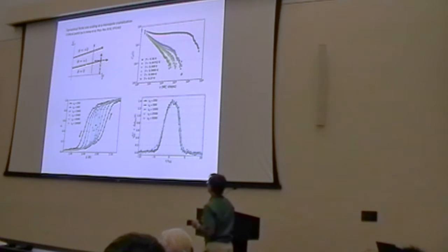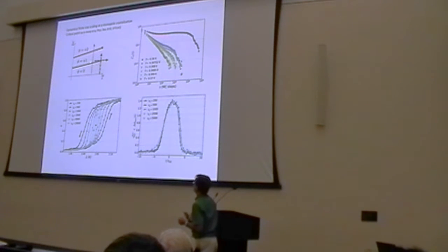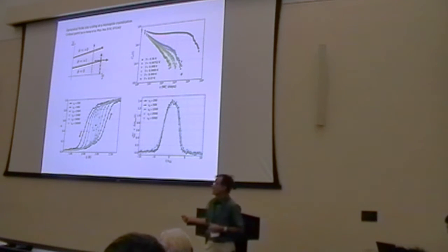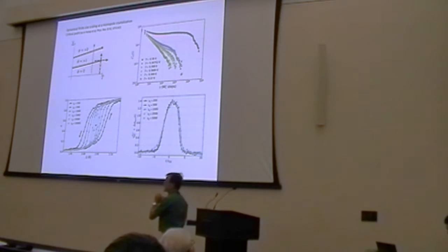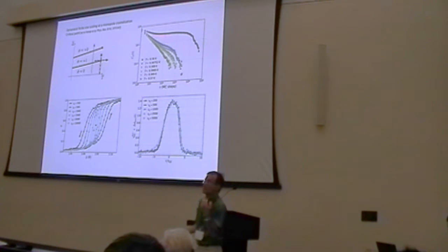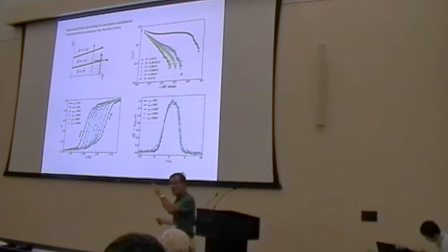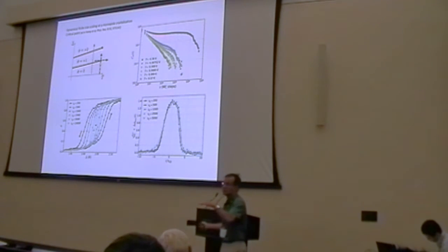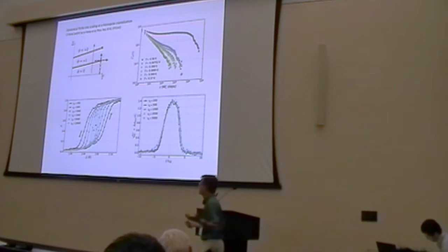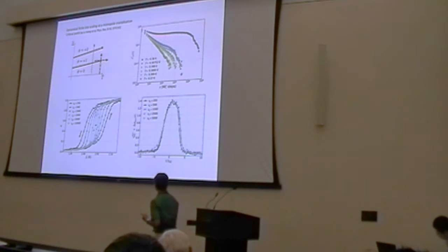And if you could find one of these planes experimentally, then in a pressure experiment you could do these dynamical experiments. As we already saw in the last talk, the microscopic time scale of these materials is typically a millisecond, so this would be an extremely interesting proposition, because this critical slowing down would enter directly into the window of experiments that we do.